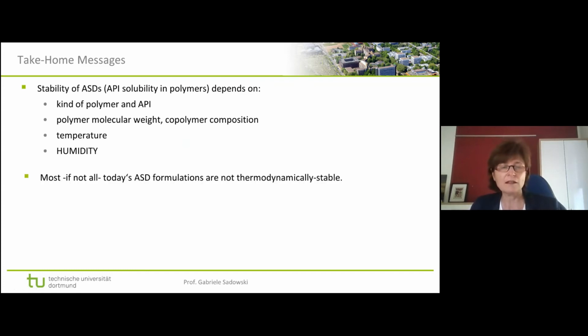This is the bad news, and I was very surprised about this, and this means we have to be very careful. We have particularly to avoid humidity, because usually the tablets we have will change with time. What the pharmacists do to avoid that and to keep humidity out is they put the tablets into blisters. And this is for good reasons, as we have seen. So once you have a blister at home, leave the tablet in the blister as long as you can, and only take it out immediately before you take the medicine. So this is really thermodynamically meaningful.